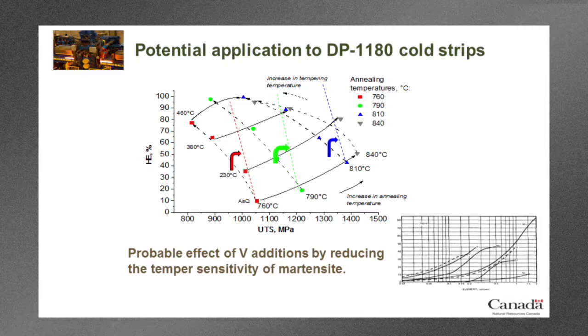So in that case, what would happen is that this dotted line, if we added vanadium, would actually shift, and it possibly would follow something like the line I've indicated here. And then for all these other intercritical annealing temperatures, where there's even more martensite present, that behavior would be the same. So we've shifted this process map. This corner would actually go up into the area that's more interesting to us, where we would have higher hole expansion and higher strength.